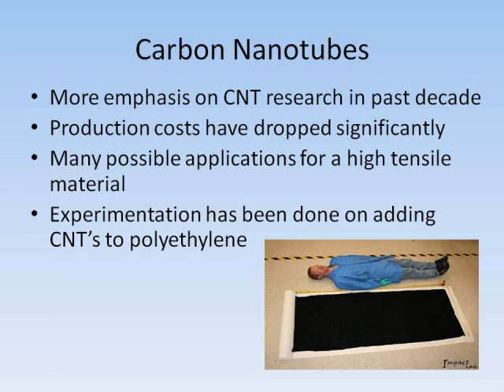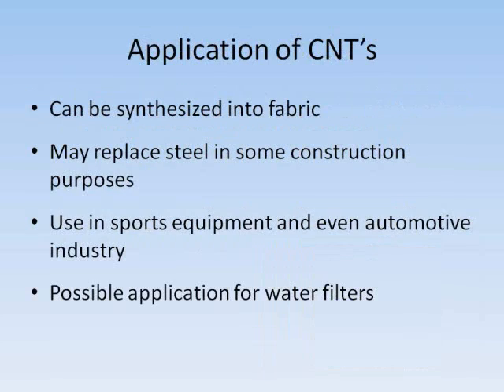The goal now is to make the production costs of CNTs as low as possible. There are many possible applications for an extremely high tensile material. Carbon nanotubes have been added to polyethylene, increasing its elasticity by 30%. With this in mind, it can be synthesized into fibers, allowing incorporation into waterproof, tear-resistant clothing. It can also be applied to combat protective suits, offering the wearer a lighter vest with enhanced protectiveness. One test used material produced from carbon nanotube fibers with polyvinyl alcohol, which requires 600 joules per gram to break, compared to conventional Kevlar used in bulletproof vests, which requires only 27 to 33 joules per gram to break.